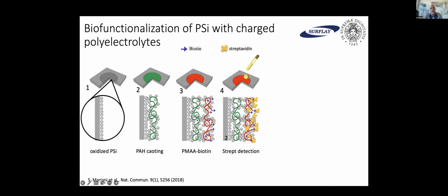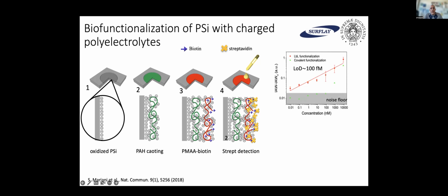But the nice thing is that we can also do the synthesis of the polyelectrolyte to already carry a bioreceptor. In this way, we don't have to add the bioreceptor after the functionalization, but we engineer the polyelectrolyte with a specific bioreceptor, and then we do the assembly in the porous silicon. In this way, we know the amount of bioreceptor we bring into the porous silicon sensor. And in this first paper we published a few years ago, we demonstrated that it was possible to really push the detection limit of porous silicon biosensors with this functionalization approach. We got a limit of detection of roughly 100 femtomolar for streptavidin.